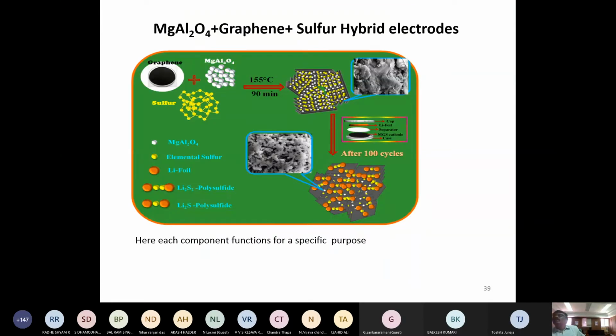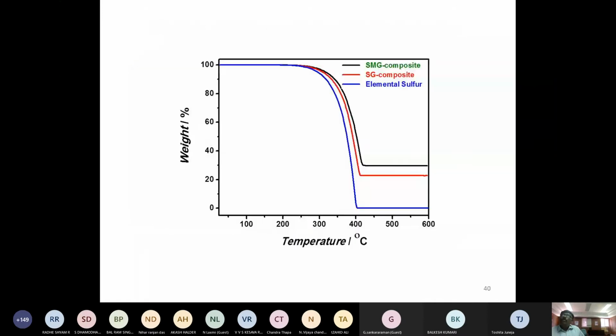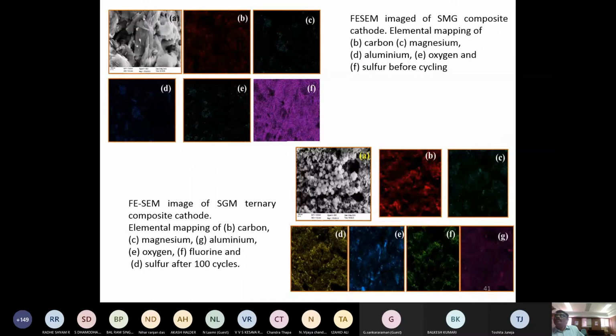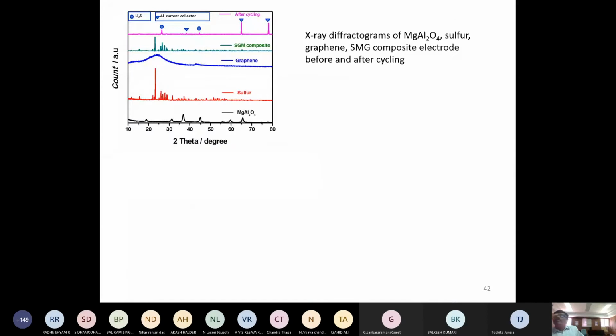Then what we have done is, instead of the sisal carbon system, we have made MgAl2O4, magnesium aluminate, graphene and sulfur hybrid electrodes. Here, each component functions for a specific reason. For example, magnesium aluminate is used to improve the stability of sulfur. At the same time, it also captures the polysulfides and prevents the shuttling due to its electrostatic attraction. And of course, the graphene enhances the electronic conductivity, and sulfur is involved in the oxidation reduction process. Here, this is the thermogravimetric analysis. We have measured the content of sulfur here, and we have identified the presence of the element using elemental analysis, and we have confirmed the presence of sulfur with XRD and other characterization techniques.